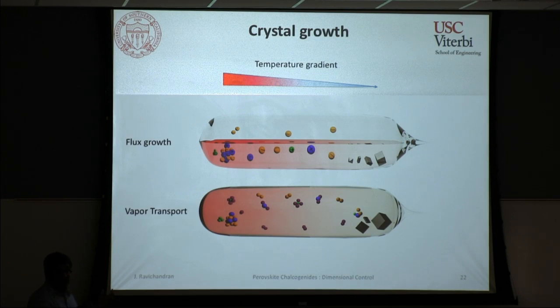So you take flux, which is basically some sort of a low melting point material that you can mix this material with, and that allows you to dissolve the whole thing, and then when you cool it down, you recrystallize and you can grow crystals out of it. The other method that I'm going to show for the later half is the vapor transport method. We'll talk about that later, where we'll grow the next set of materials.